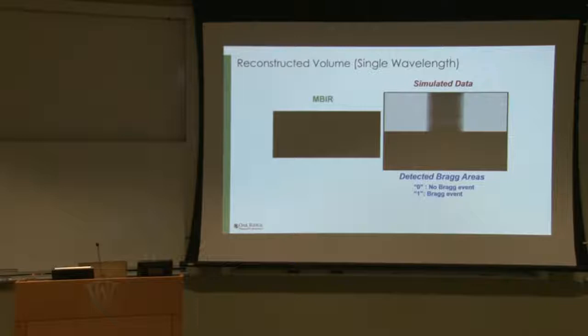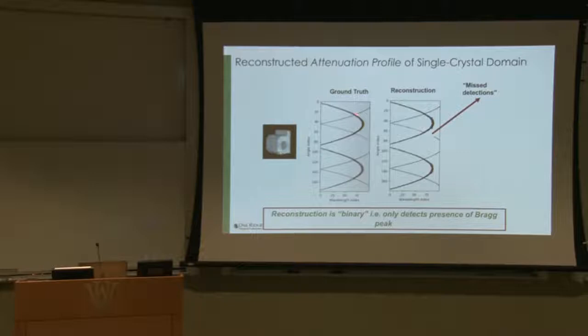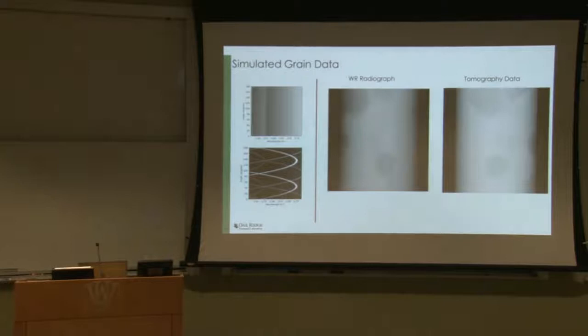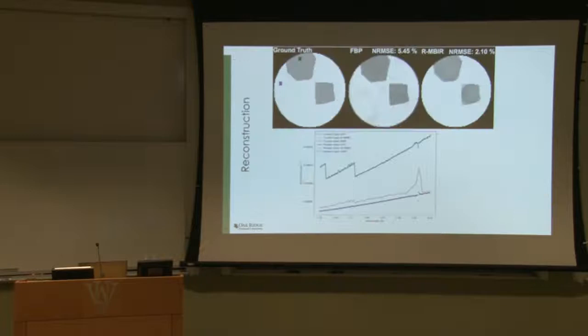And this is an example of the crystalline signature. So this was the ground truth, and this is what was obtained by the algorithm. So it does a pretty good job of identifying when this component went into the Bragg condition. And we have done this on other simulated data sets also, where again, we have data like this, and the goal is to do a 3D reconstruction. And again, compared to the existing techniques, we can get a pretty significant improvement. And these are hyperspectral. What you're seeing is the answer at one wavelength, and you can plot, for example, the pixel values as a function of wavelength.